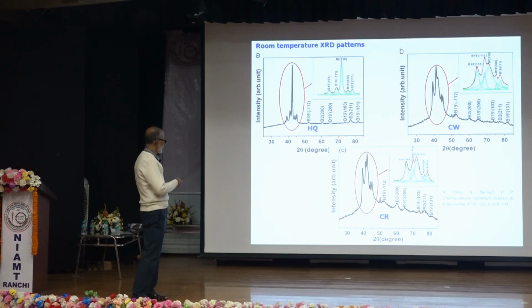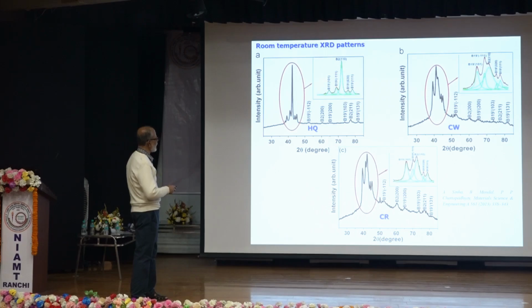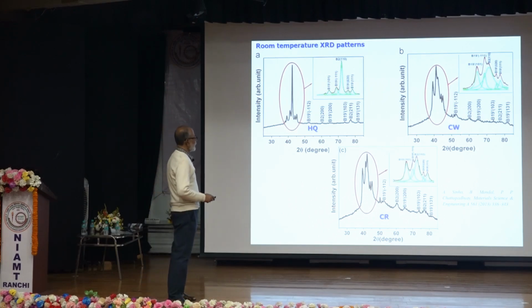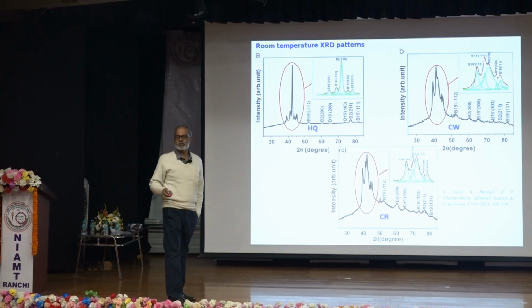So this is the room temperature XRD, and here there are a lot of peaks. So we deconvoluted the peaks. This is for the homogenized quenched sample. We found a significant amount of parent phase and a certain amount of martensitic phase. Now we cold worked, and there we find that we got a significant amount of martensite. So the amount of martensite is increased by virtue of deformation induced transformation, as we have discussed. The application of strain transforms austenite to martensite. So by deformation, we got a higher amount of martensite, and that is true for cryogenic treatment.